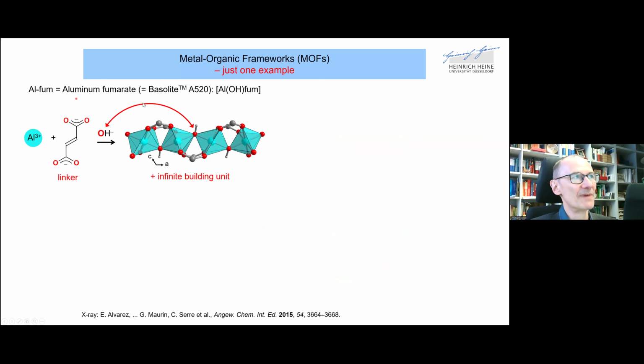It's aluminum fumarate, and also called Basolite A520, because BASF has first made this metal organic framework. So the building blocks are a little bit more simple: aluminum ions, the fumarate linker, and a hydroxyl group. And then you have here a chain of octahedrally coordinated aluminum atoms, and the octahedral coordination comes about by bridging hydroxide group and the bridging carboxylate groups from the linker.